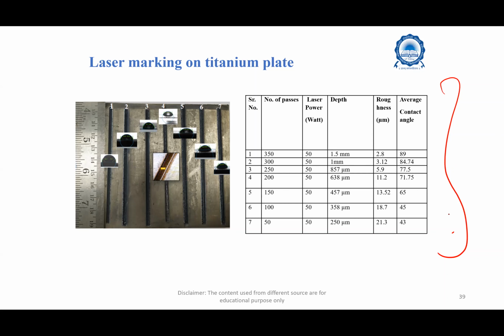So the roughness profile reduced with an increase in the number of laser passes due to the consistent impact of the laser beam irradiation and the rapid vaporization of the material.